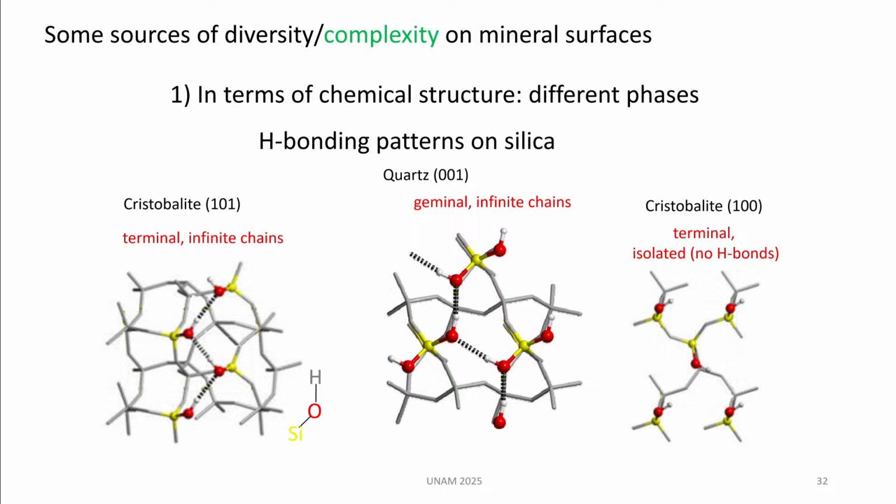And finally, and here I'm anticipating on the next slide, this is also cristobalite, but it's a different plane. Here, the geometry is different. The OH groups, the silanols, will also be formed, but they will be too far from each other, and they will not be able to interact and to form H bonds. They will be isolated silanols. And each one of these patterns has a different reactivity for adsorption.